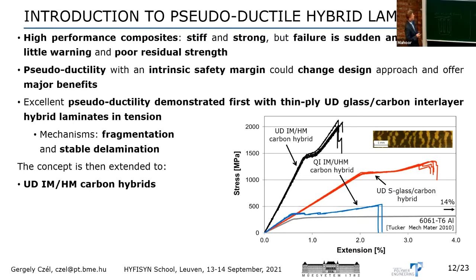But what we have seen during the test when we failed to produce ductility is that when we have a single delamination, we can very accurately monitor the failure strain of the low strain component in our hybrid, meaning the carbon epoxy ply. And so we thought, why shouldn't we exploit this for developing a new test specimen, a new test method for unidirectional, not hybrid, but monolithic composites to determine the failure strain in a better way than what we do according to the standards.